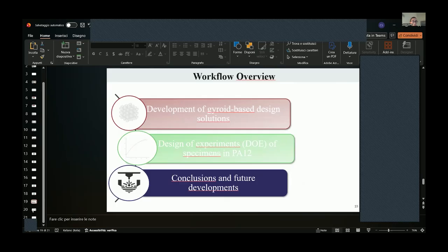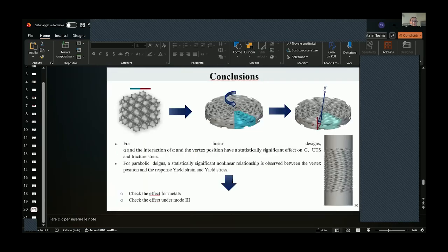So let's go toward the conclusions. So we have demonstrated that for linear designs, if we want to maximize the torsional stiffness, UTS, and fracture stress, we have to choose a condition in which the angle is equal to 10 degrees, and that for parabolic design, the best condition to maximize yield strain and yield stress is the one in which the vertex position of the parabola is in the middle of the specimen.